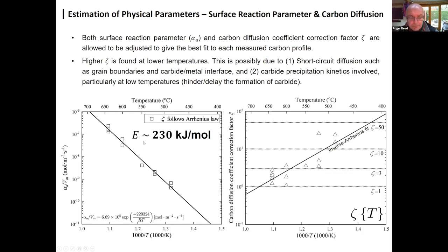So you can see here that although we came up with a very nice estimate for the kinetics of the Boudouard reaction, this alpha parameter here normalized against the molar volume, we have come up with what we believe to be some of the first kinetic data for the Boudouard reaction.